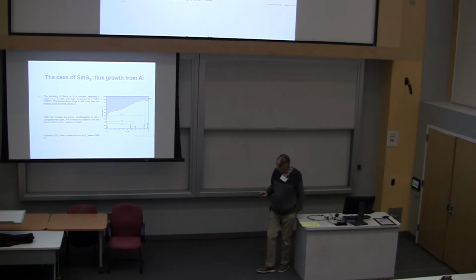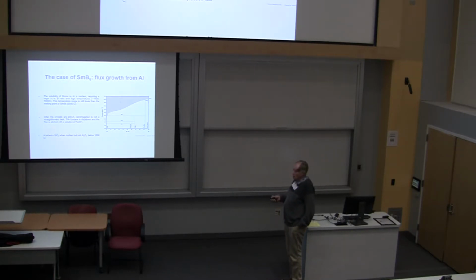And so in order to grow samarium B6 from this kind of melt, you actually have to go to fairly high temperatures, usually in a silicon carbide furnace, go to close to 1500, maybe 1450, which gives you more lifetime for your furnace elements. But then you have to do this under a cover because you can't encapsulate the crucibles in quartz to work at those temperatures. But you can etch the crystals out using sodium hydroxide, which does not attack those particular crystals.